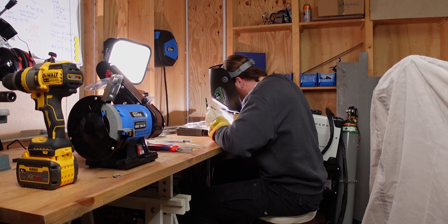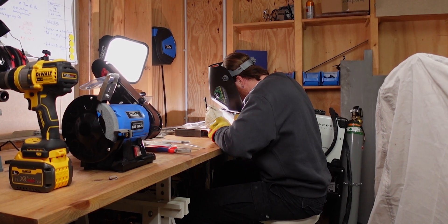In the category of mild steels, there's another one very interesting for custom bike building: category four — chromoly. The name chromoly comes from its two alloying elements, chromium and molybdenum, and those two give it special characteristics. Due to the alloys, it has a much better strength-to-weight ratio and is much harder and stronger than regular carbon steel — basically carbon steel on steroids. However, these advantages also have downsides: it's much harder to work with than regular carbon steel, especially when welding. Because it's so heat sensitive, you need to keep a few special things in mind to avoid cold cracking. The best chromoly for custom bike building is 4130.